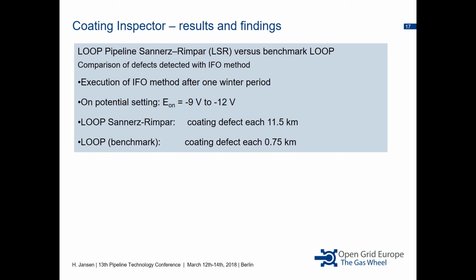The second key factor that we used was the so-called IFO method. IFO method is a method that was developed in Germany to detect small coating defects on a pipeline. It is similar to the DCVG method, direct current voltage gradient measurements, that you can find also in the international standard. We carried out this IFO method after one winter period so that we are sure the pipeline has sufficient ground contact and we find all coating defects. And we put on potential of -9 volts to -12 volts, with this negative on potential, to find also smaller coating defects.